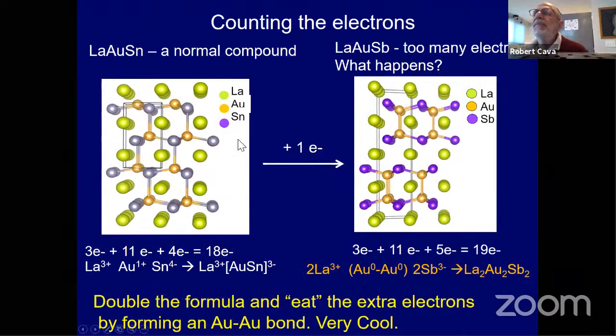if you look at lanthanum gold tin, so now we're going to compare lanthanum gold tin to lanthanum gold antimony. You don't have the periodic table memorized, but tin and antimony are right next to each other in the periodic table. Antimony has one more electron than tin. So lanthanum gold tin has 18 electrons, and it's a semiconductor. And it has this crystal structure over here where every gold is bonded to a tin. I'm sorry about the picture. Every gold is bonded to a tin. And it's just a normal 18 electron compound, and it's a semiconductor.